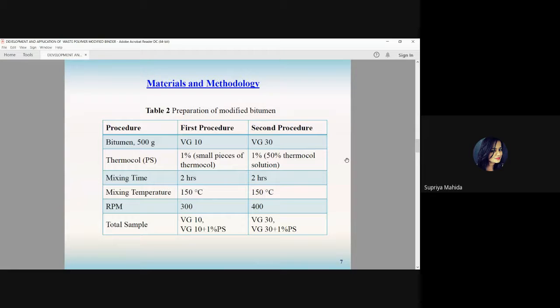The second process suggests that we prepare a 50% solution by adding 50 gram of polystyrene to 50 gram of organic solvent, where we get a proper homogeneous mixture of 50% thermocol solution. That thermocol solution we add drop by drop to 500 gram of bitumen, and stir it for 2 hours at 400 rpm at 150 degrees Celsius. In the second procedure we adopted VG30 grade, and in the first procedure we adopted VG10 grade of binder. So in total there are 4 types of samples: 2 conventional and 2 modified binders.